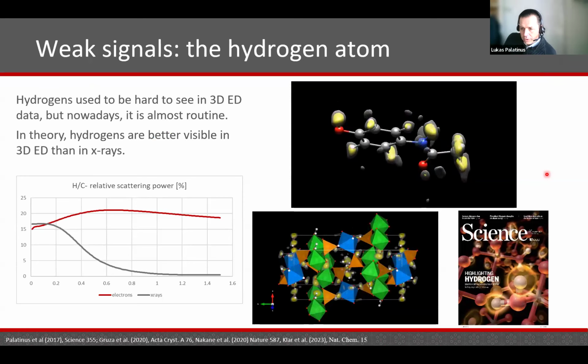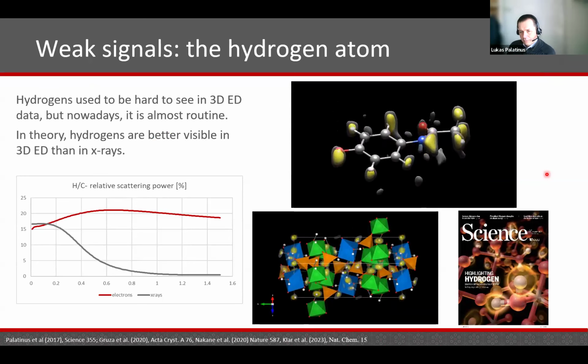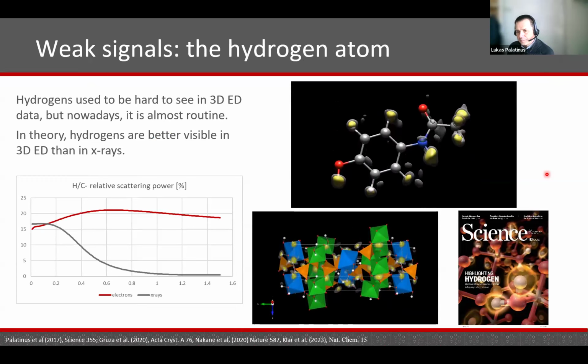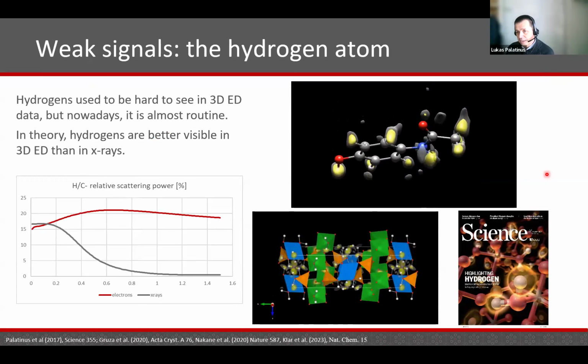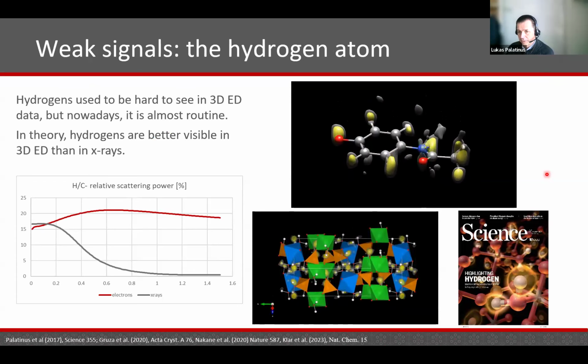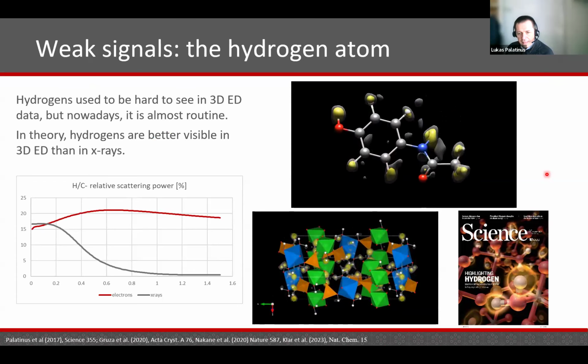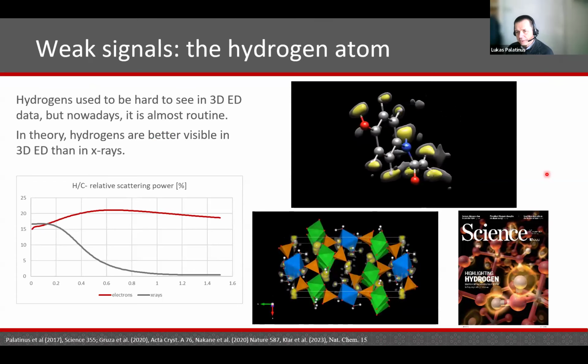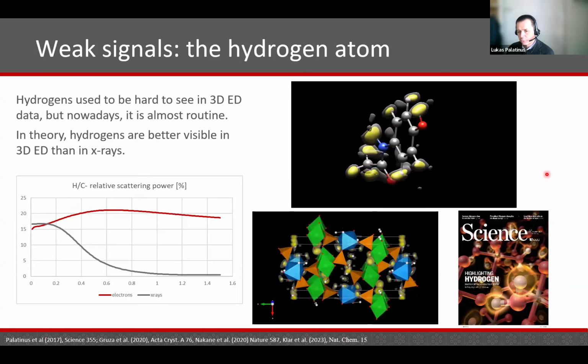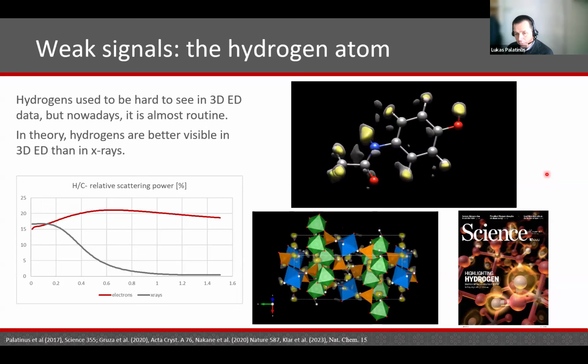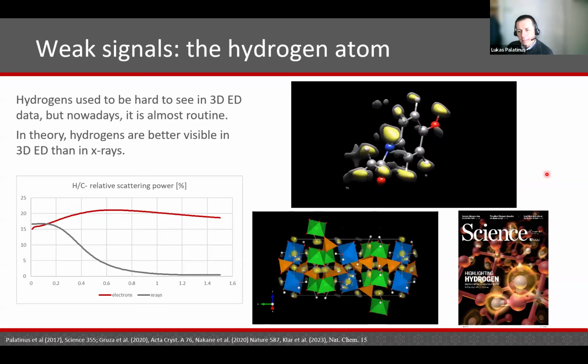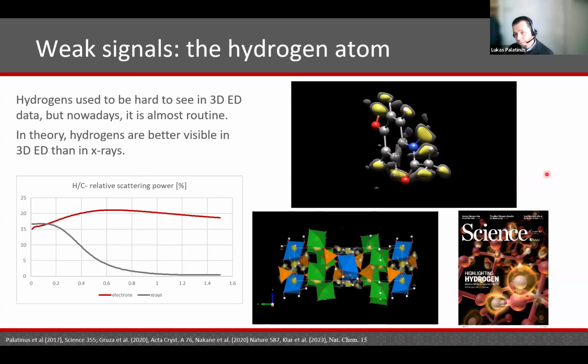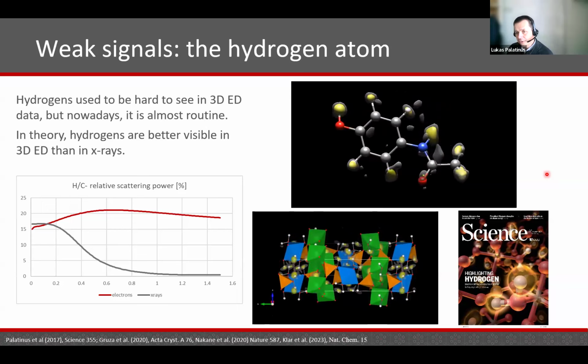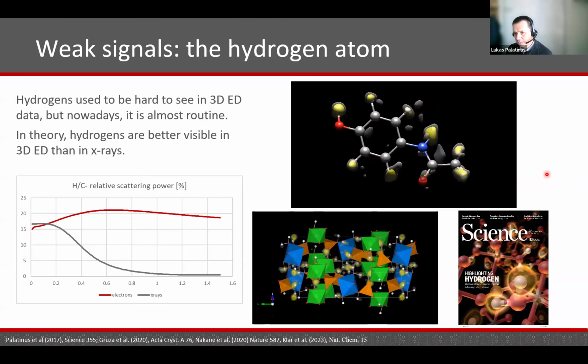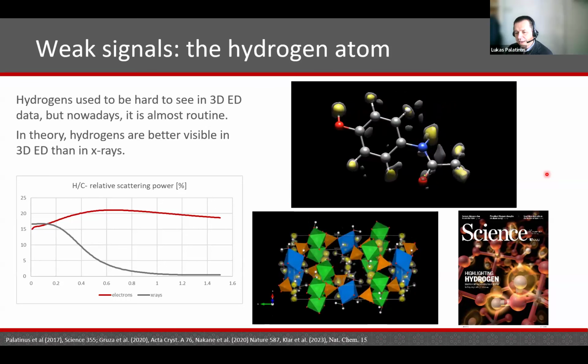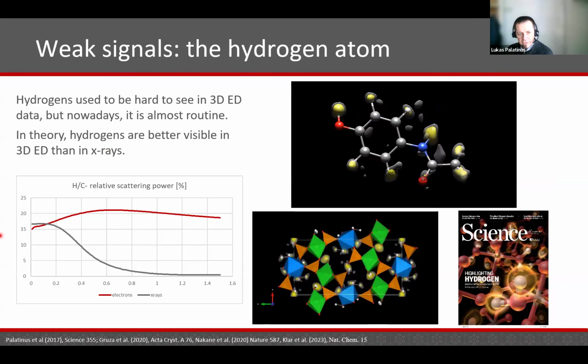So I mentioned that one of the advantages of 3D electron diffraction, and especially dynamical refinement, is that we can see weak signals in crystal structures. Of course, the weakest scatterer is hydrogen. That's true both for X-ray diffraction and also for electron diffraction. But in electron diffraction, hydrogens are relatively heavier compared to heavier atoms than in X-ray diffraction. That can be seen here on this plot.